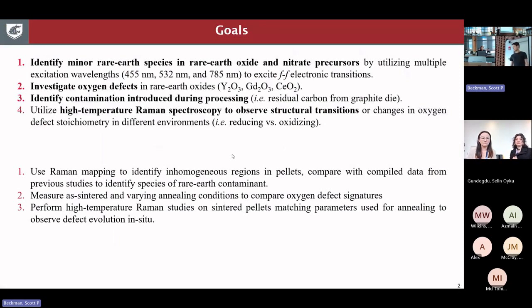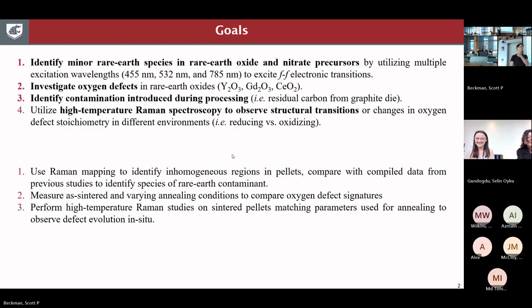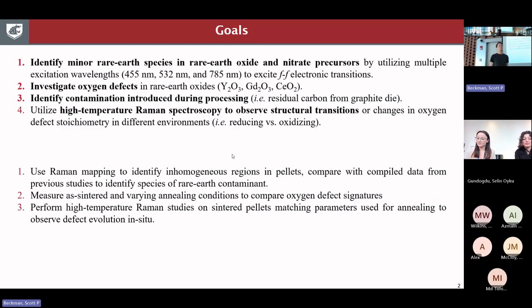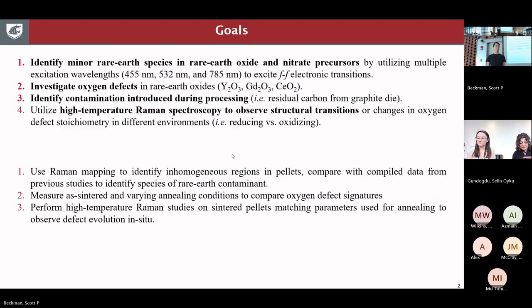The main thing I've been looking at is using our Raman spectrometer as a photoluminescence tool to look at the luminescent signatures of various rare earth elements, which are significantly more intense than the Raman spectra. This allows us to compare with a compilation of data that we've collected on binary rare earth oxides and use these very intense signatures to identify the presence of rare earths even in very small amounts.